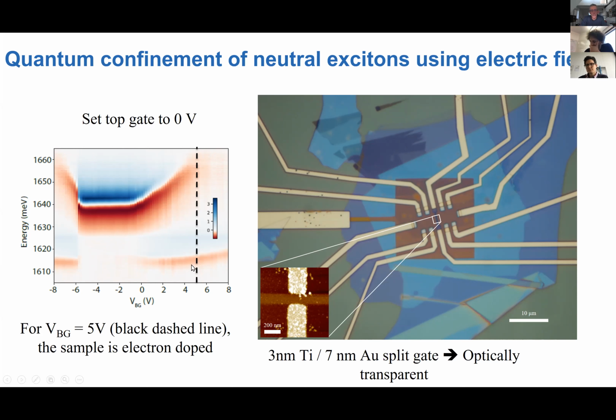The lines are broader. And what I would like to do is to focus on this 5-volt backgate voltage, where most of the material is heavily electron doped, as you can see from the presence of the attractive polaron line and the relatively large blue shift of the repulsive polaron. So now the question is, we take this device at 5 volts backgate, and we're going to apply a voltage on the top gate and start reducing this top gate voltage.